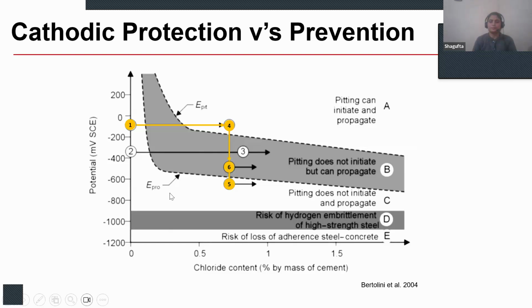However, in cathodic prevention, which is applied to structures that we know will face corrosion problems in the future, what we generally do is apply the system from the onset of construction. As a result, we initially bring down the potentials to a more negative direction, like around minus 400 millivolts. So even if the chloride content increases with time, instead of moving to zone A, it still moves to zone B. That's the concept behind cathodic prevention systems.